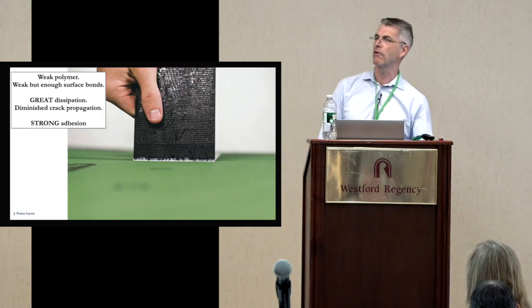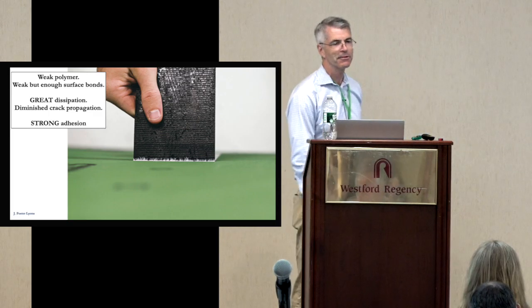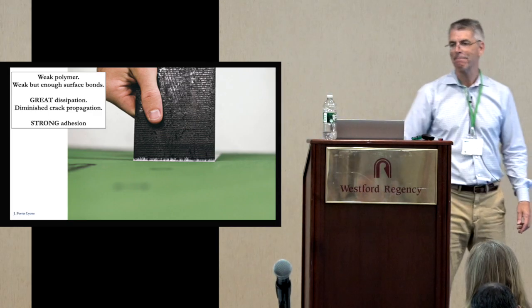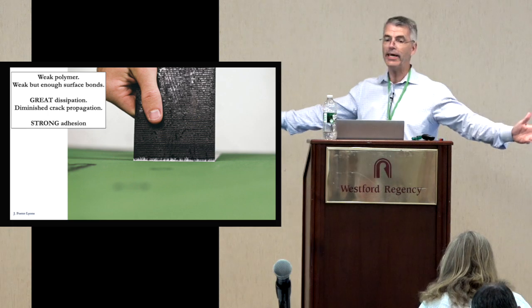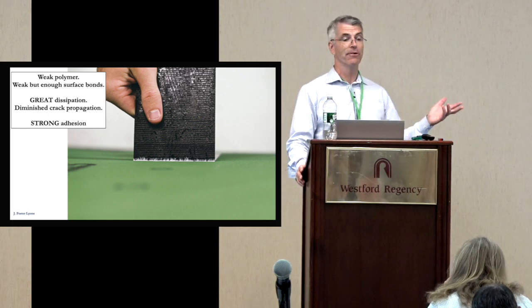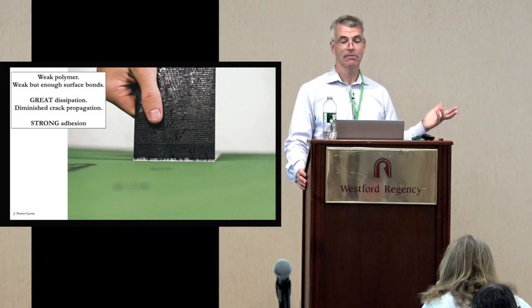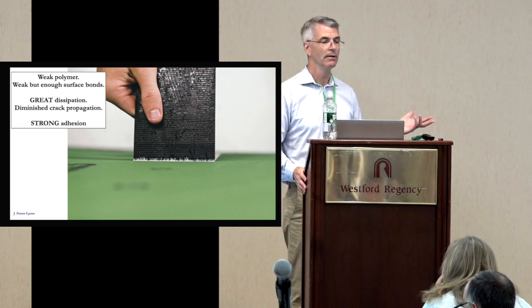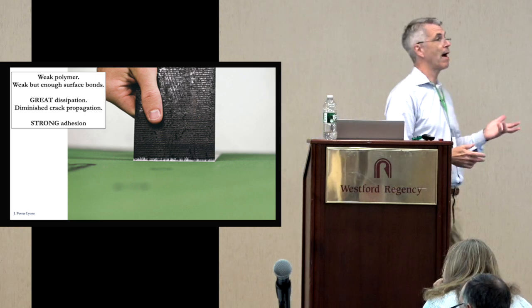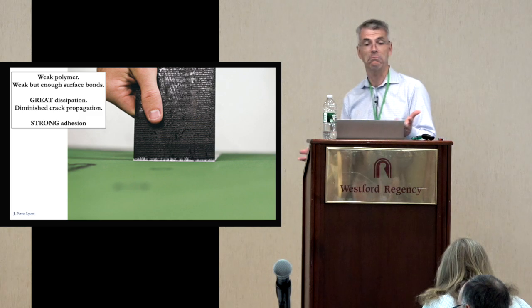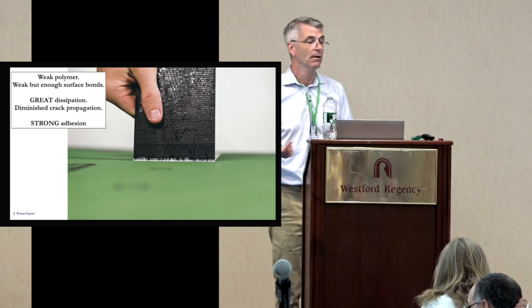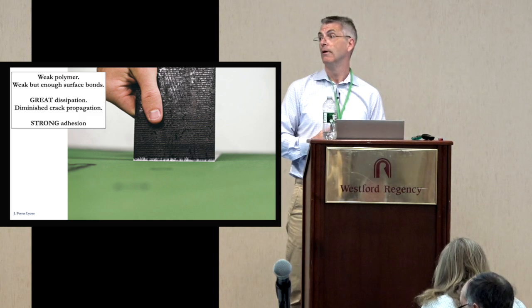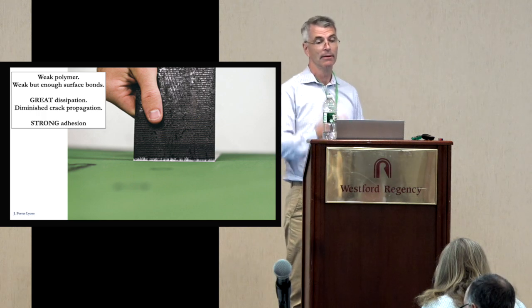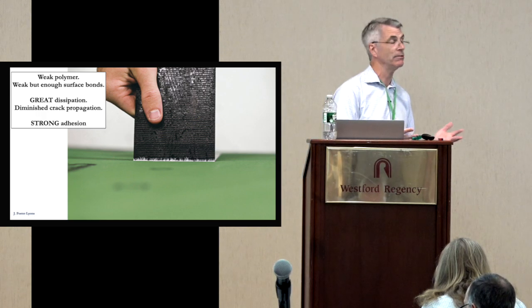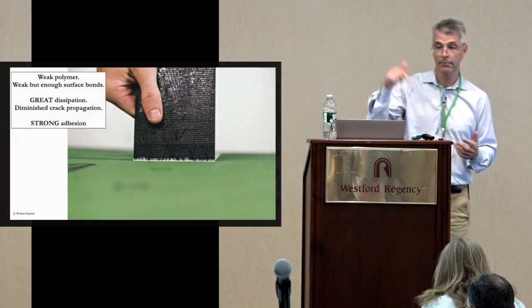All right, and I don't know whose material this is, but one of them's green on a surface and the other one's black in the tape. Same thing. It's a weak polymer, but it's got enough of these surface energy bonds to hold the polymer to the material. There's great dissipation. There's probably a little bit of intermingling, although I'm not sure of that at all. But there's certainly great internal entanglement within the adhesive on the tape. As a result, you get tremendous reduction in crack propagation, and you get strong adhesion.